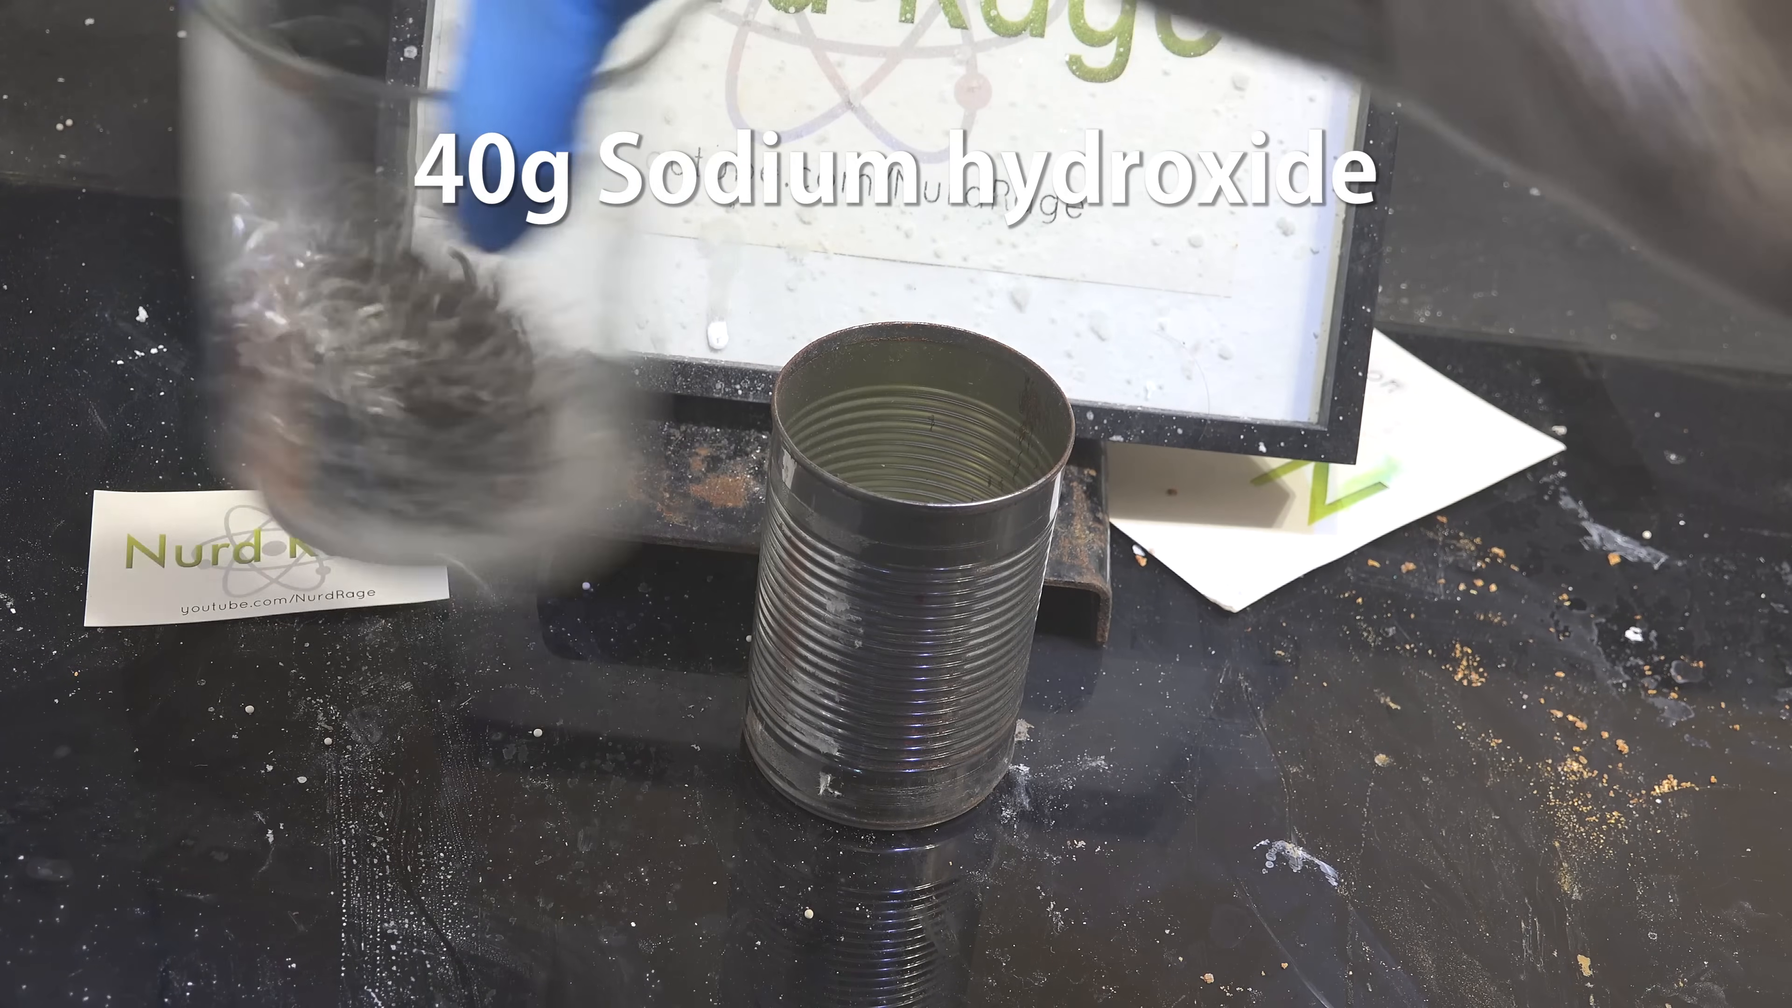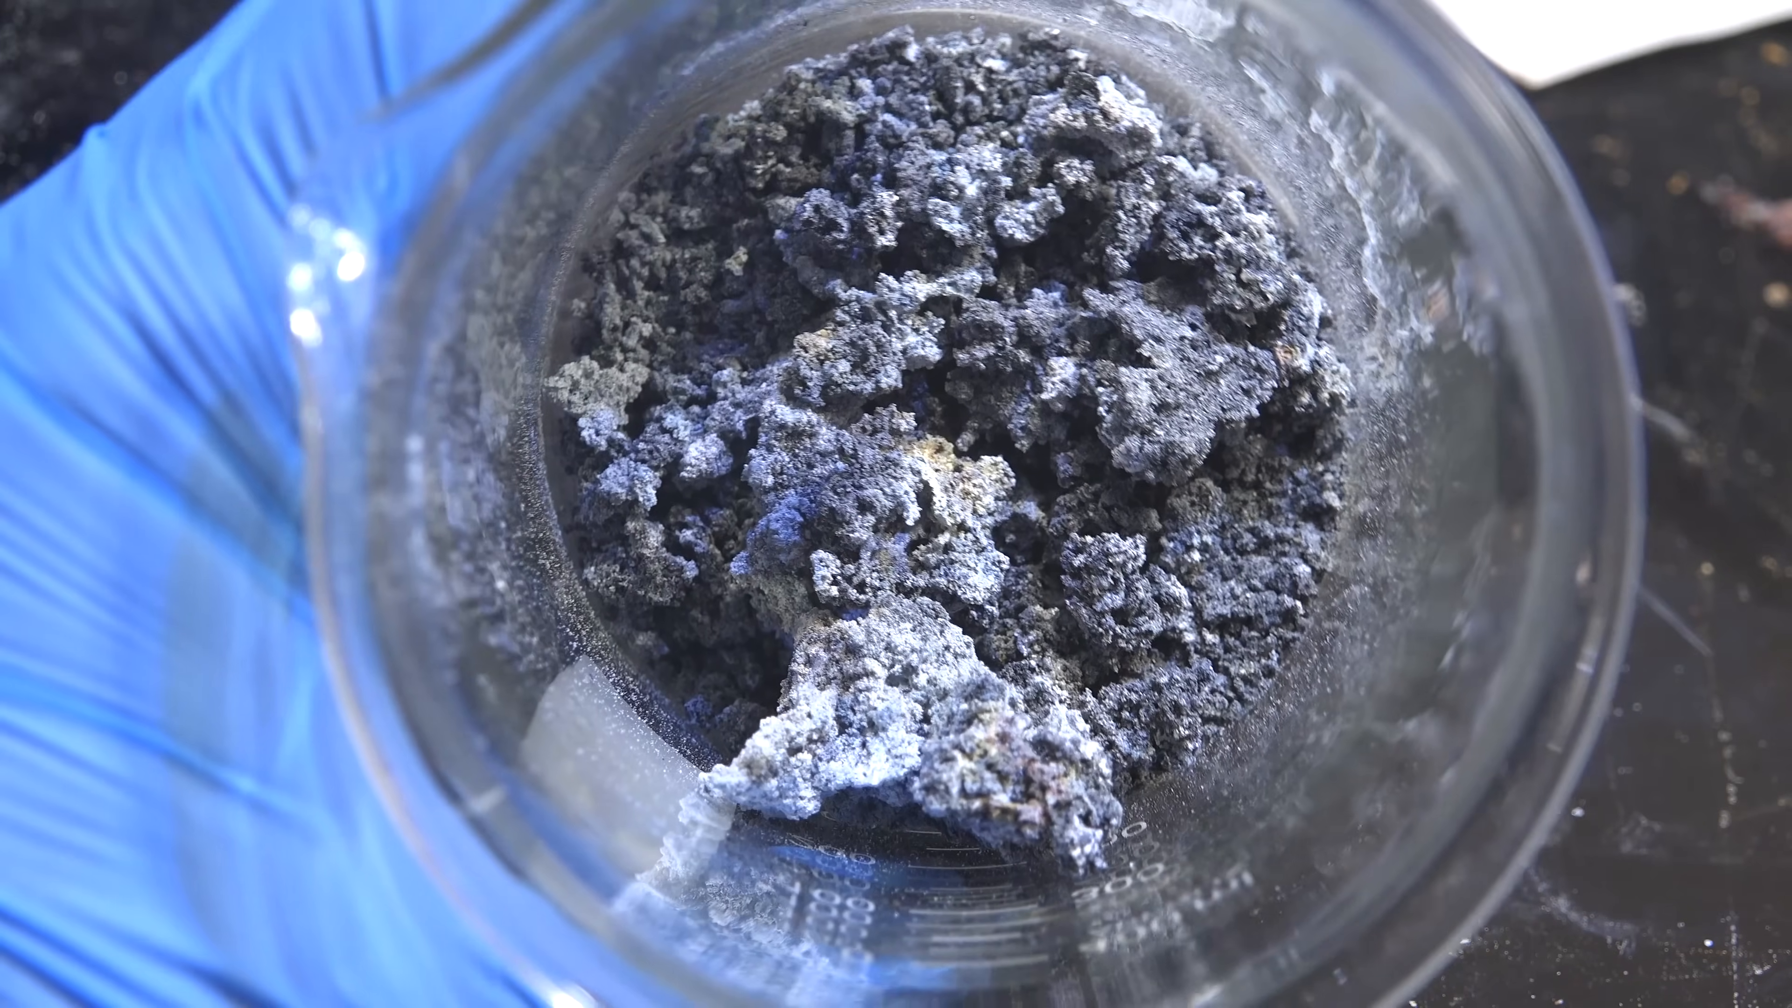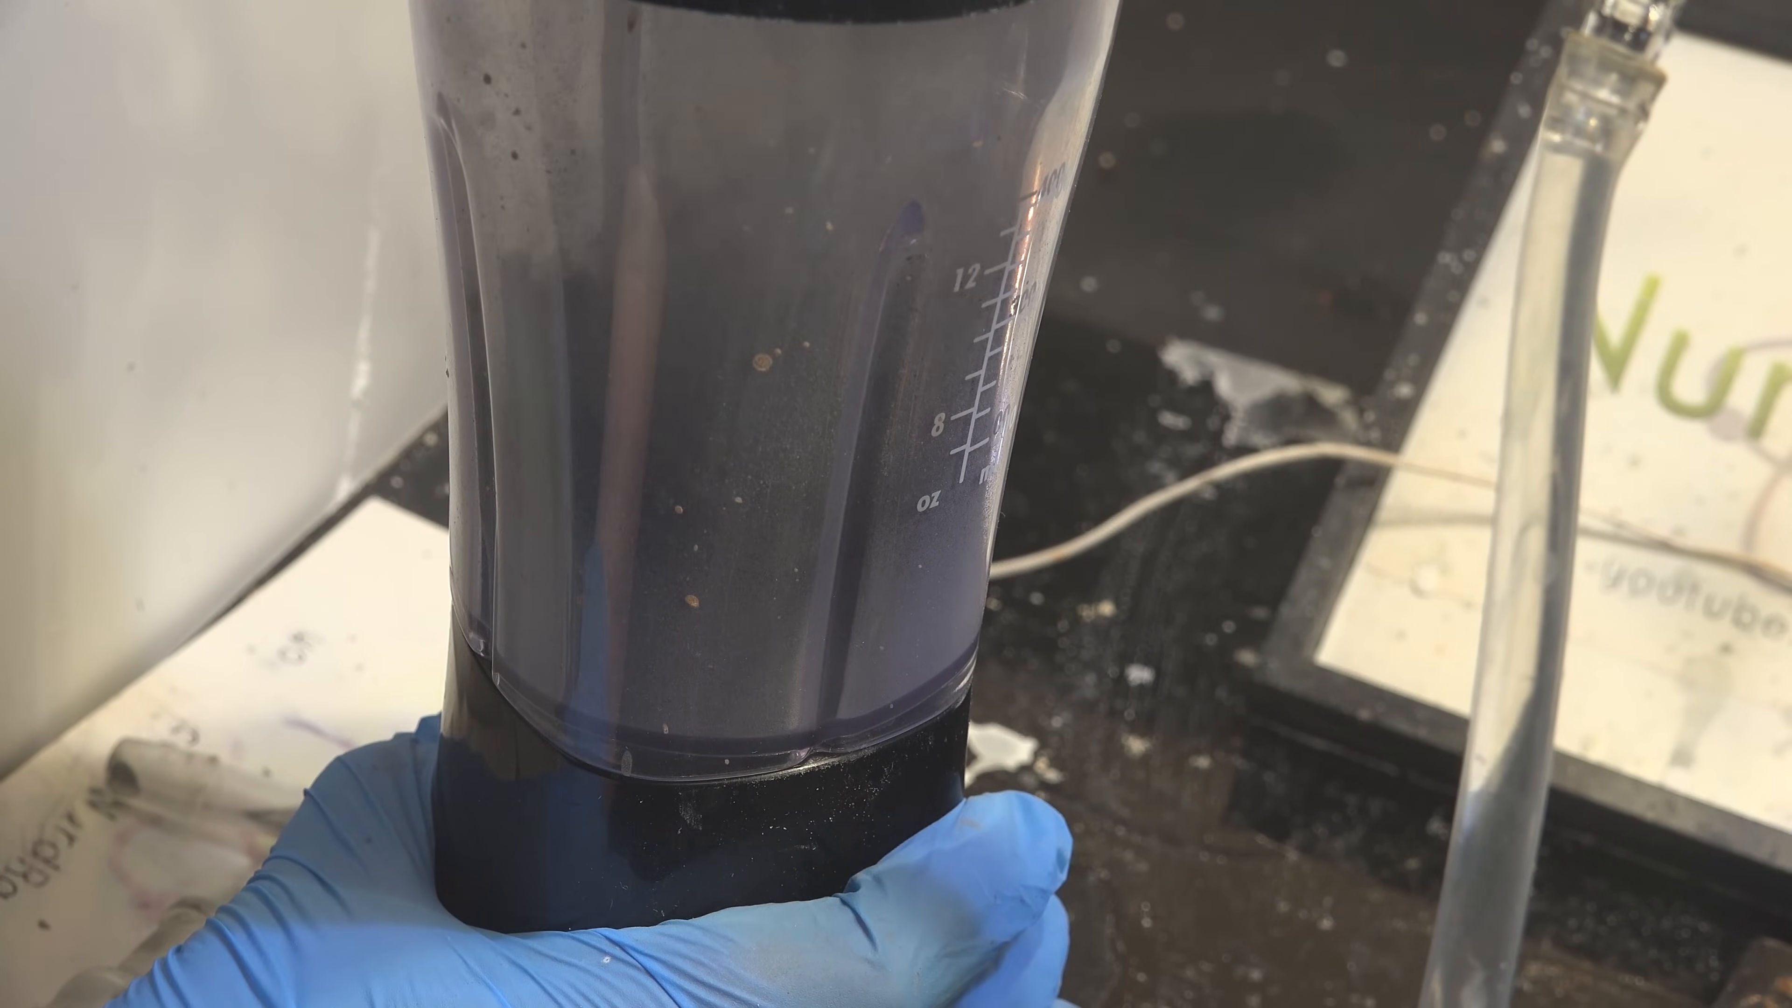But briefly we will react sodium hydroxide with a stoichiometric excess of magnesium metal in an air free environment. It is here where we are actually making sodium metal. Upon cooling this produces sodium magnesium oxide aggregate that we chisel out. This is actually the easy part though. The much harder part is separating the sodium in the aggregate from the magnesium oxide slag. To do this take this aggregate and grind or blend it into a powder. Doesn't need to be too fine but the pieces should be small enough that solvent can thoroughly seep in. The consistency of coarse sand is acceptable.